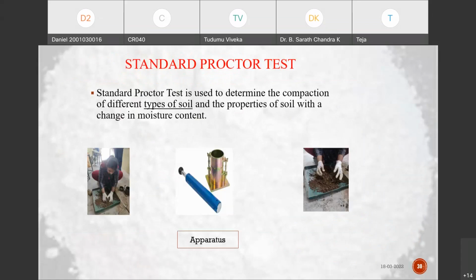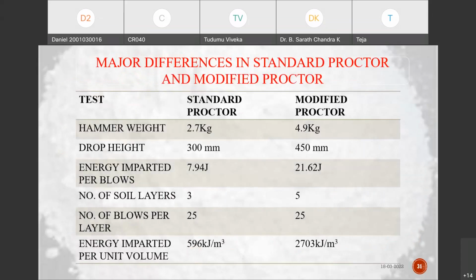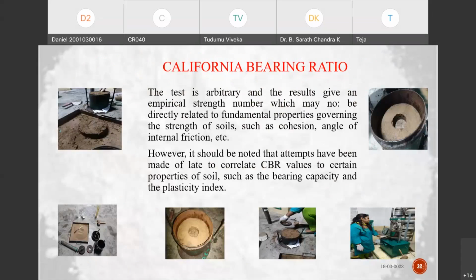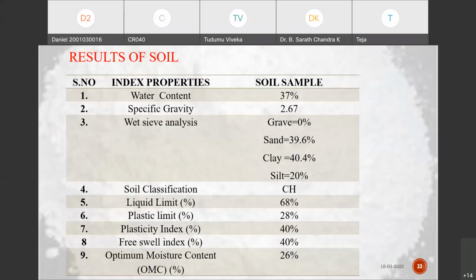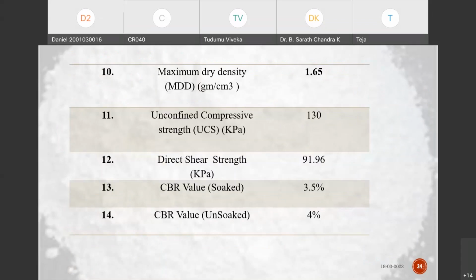Compaction tests: there are two different tests used, standard Proctor and modified Proctor, and these are the major differences between them. Coming to the California bearing ratio, these are the results obtained for the soil. Water content is 37%, specific gravity is 2.67, followed by free swell index, optimum moisture content, maximum dry density, unconfined compressive strength, and CBR value, soaked and unsoaked.